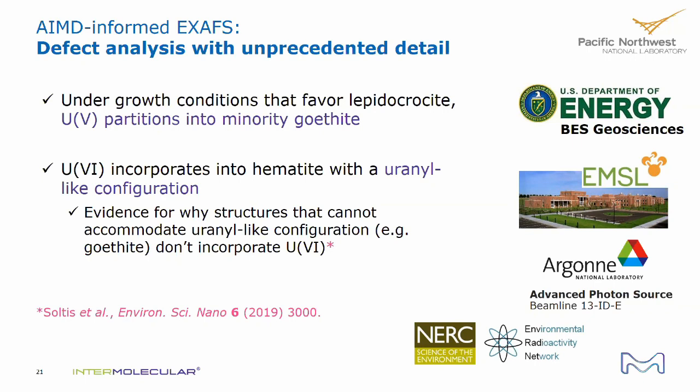Sure. So when you have precipitation of iron oxides in real natural environments in water, then we might expect that you would actually have some protonation or some incorporated protonation some way or another. You'd end up with hydroxyl groups. This has been studied a little bit as hydrohematite, or low temperature or hydrothermally grown hematite, as opposed to, say, hematite that's been sintered at 1200 C or something like that, where you might expect to remove all of the water or water-related species like hydroxyl groups.